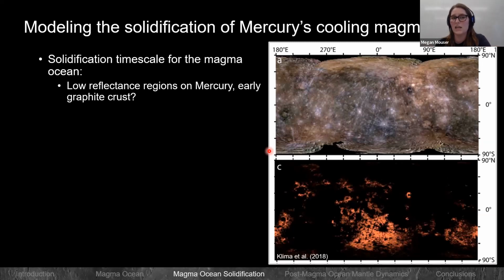So the first step to that is looking at the solidification timescale, so how long it would take for the magma ocean to cool. So some other results from MESSENGER showed that there were these low reflectance regions across Mercury, and the spectral features aligned with carbon. And so because of the reducing nature of Mercury, this is believed to be graphite. And due to the widespread nature of these deposits and their proximity to impact basins, it's believed that this could be remnants of a graphite flotation crust. So we want to test the possibility that maybe there was a flotation crust.